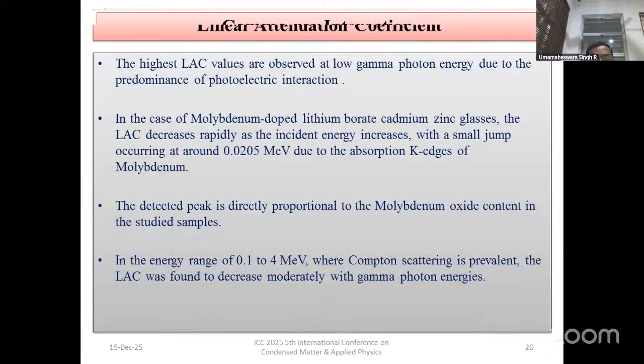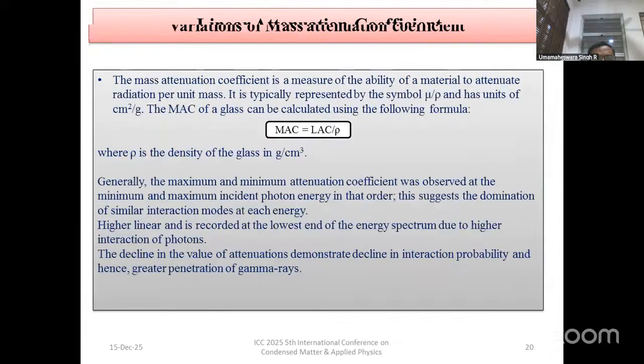And this is, if you see, the molybdenum doped with potassium and lithium I mentioned, potassium borate cadmium zinc glasses. Here LAC decreases rapidly with incident energy, with a small jump at 0.0205 MeV. And then the detected peaks are directly proportional to the molybdenum oxide content. In the 0.1 to 4 mega electron volts range, the Compton effect is predominant. Later, pair production is going to dominate.